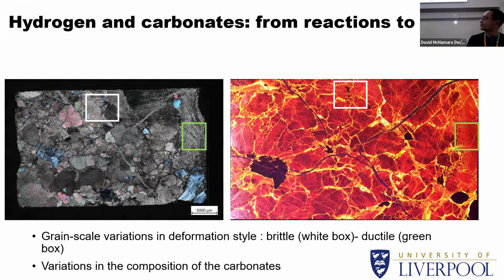The image to the left is a cross-polarized image, and the image to the right, where it looks like the thin section is on fire, is an optical cathodoluminescence map. If I look at the CL map in detail, you can see that it's not a very homogeneous composition. You've got these darker bits, fringed by bright luminescent bits. This is generally finer grained in the fringes, but you also have some darker, finer grained layers. What this points out is that there are definite variations in the compositions of the carbonates. It's not just a singular carbonate with graphite in the sample.